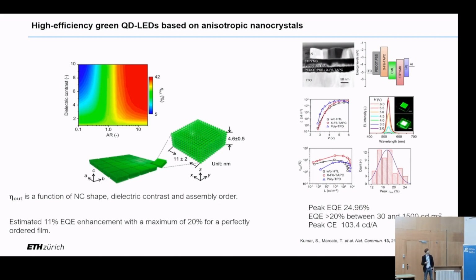And in our group, we fabricated quite efficient LEDs based on the system, which reached up to almost 25% peak external quantum efficiency. And through the model I described before, we were effectively able to link the shape and the dielectric environment of the single nanocrystal and how they assemble in the film with the anisotropy factor, which in turn can be used to calculate light outcoupling in LEDs. And so we can predict what the effect is on, let's say, an estimate of the external quantum efficiency.